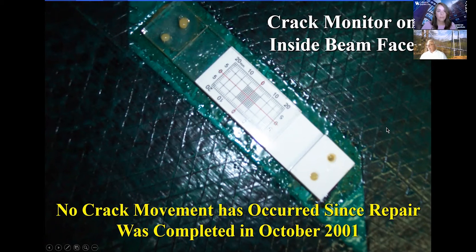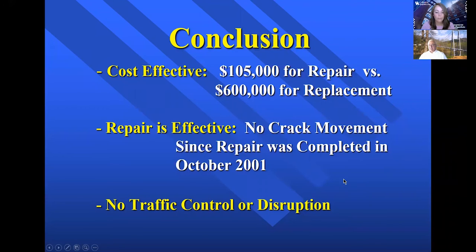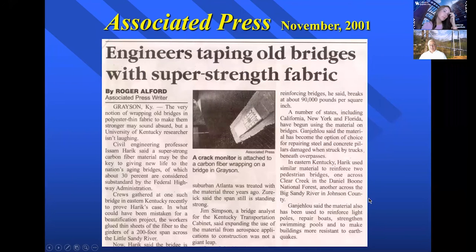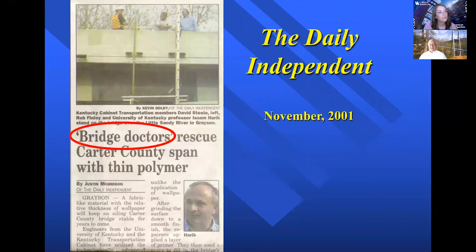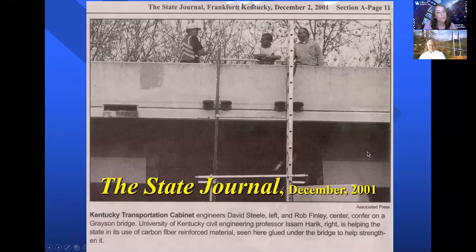But even now, in many states, people who are not familiar with these materials call this smoke and mirrors. And I wouldn't blame them. It's something new, something that's unbelievable that this can really resist that much force. But again, the proof is there. It's been almost 20 years now, and this bridge is still holding very well. So we saved the state over $500,000, and we have not seen any cracks anymore in this bridge. But more importantly, there was no traffic control whatsoever on this bridge. So again, this received a lot of attention nationally as well as internationally.